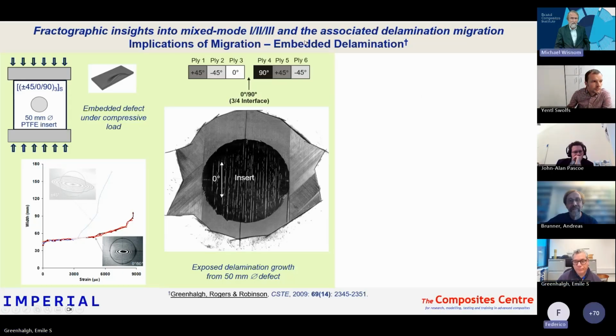I think that's very interesting. I think it just shows how important these transverse cracks are, because in allowing this migration to occur, you change the amount of energy available, and therefore can change the degree to which it propagates, as you show very nicely there. Yeah. And switching to another thing, if you use thin plies, then you tend to suppress this matrix cracking, and that may actually change migration and therefore the delamination behavior.